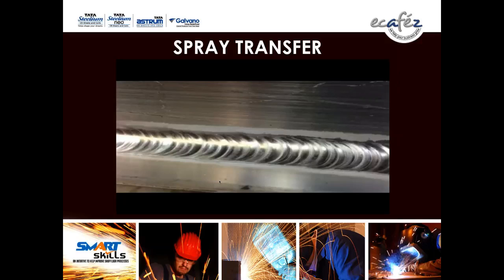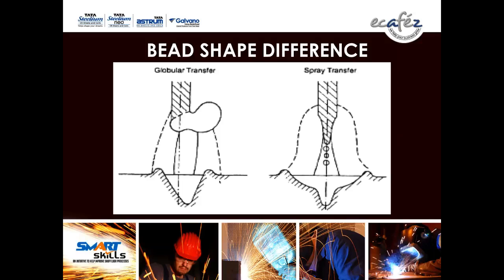So this is a pictorial view of spray transfer. Check the quality of the weld visually. This weld profile from spray transfer will give you exceptionally good results. But with globular transfer, the joint strength will be reduced, the bead appearance will be very bad, and good penetration will not be available. So always go for either dip transfer or spray transfer. Don't use globular transfer.